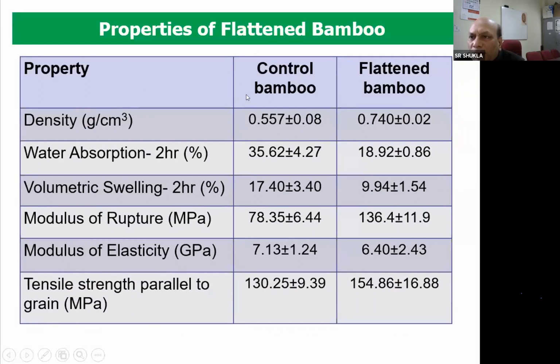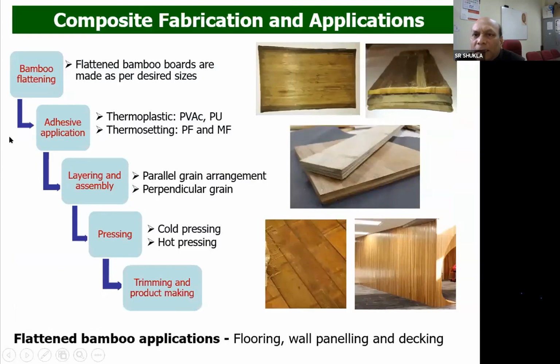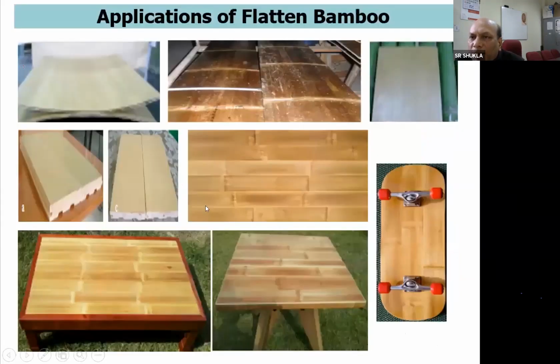So here is the table which shows the control bamboo properties and flattened bamboo properties. These are the different properties like density, water absorption in 2 hours, volumetric swelling in 2 hours, modulus of rupture, that is the bending strength and bending stiffness, and tensile strength parallel to grain. We can see that flattened bamboo carries much better properties because of the densification and the composite properties. These are the different applications of the flattened bamboo, like it can be used for flooring, wall paneling, and decking. These are the different products which can be made from the flattened bamboo.